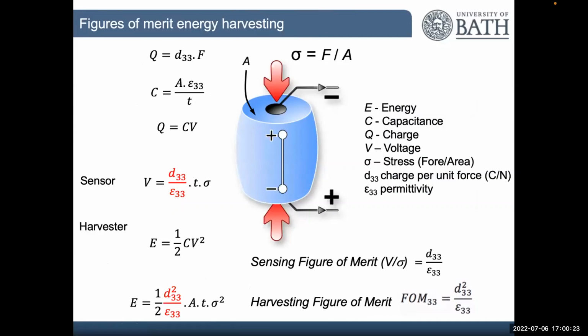And again, I work in energy harvesting. The energy generated is half CV squared. And so again, I can use this equation and put it in here. I have my very simple parallel plate equation. So I can work out the energy generated for an applied load. And again, it's proportional to the volume, proportional to stress squared. And again, these are the material properties, D33 and permittivity. So I want high harvesting figures of merit. So high voltage, we require D33 divided by permittivity. High energy, we want high D33 squared divided by permittivity. So similar, but some small differences.